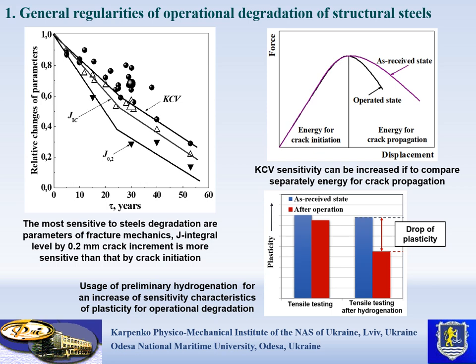Usually, characteristics of plasticity are less sensitive for evaluation of operational degradation in comparison with impact strength and fracture toughness. However, the sensitivity of plasticity characteristics can be increased if we compare unoperated and operated states of steel after preliminary hydrogenation of the specimen before tension. On the left, you can see a little difference between plasticity of different states of steels, but the right scheme demonstrates essential difference if we compare results of tensile tests of hydrogenated specimens. It should be noted that the method of preliminary hydrogenation can be used independently of whether operational conditions include aggressive environment or not.